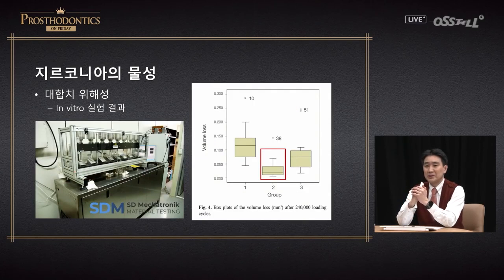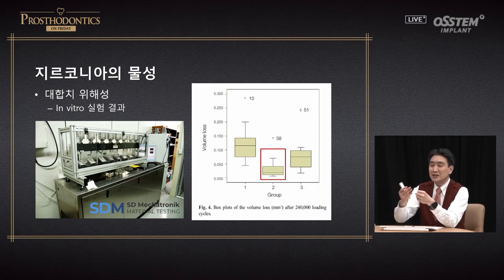In 2010, so 10 years earlier, equipment for wear tests became available at my university. I was curious, so I did the test. To give you the conclusion, if you look at the very left one, this is feldspar material, porcelain. Second is zirconia. When you provide a zirconia prosthesis, the level of wear on the natural and opposing tooth is very low, less than half. Third is coloring glazed group on zirconia.